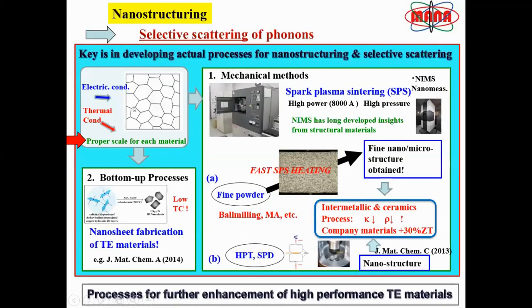And the key of nanostructuring is basically that it utilizes the fact that the electrical carriers and the phonons which carry the thermal energy have different length scales. So basically, for a thermoelectric material, usually the electron mean free path is small. And if you can make a nanostructure or nano-microstructure in your material, the phonon mean free path will be very effectively scattered. And the electrical part may have a small penalty, but still the phonons will be blocked more, the heat will be blocked more.